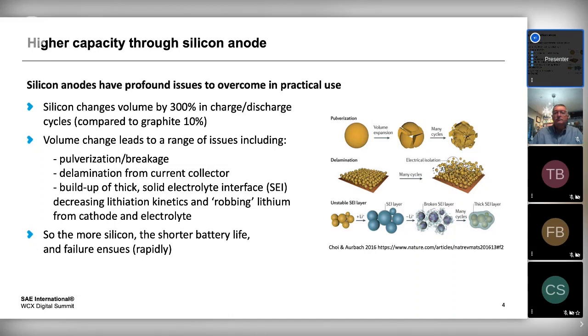What happens is the silicon particles themselves will pulverize and break under that volume change, and they won't go back together. The entire particle system will try and lift off of the copper current collector. And more importantly, when the particles break, they increase their surface area. That extra surface area means more lithium gets sucked out of your electrolyte and your cathode to form the solid electrolyte interface, which is the thing that coats the particles the instant you charge a battery for the first time. Once that lithium's gone out of the system and it's stuck in a solid interface on the anode particles, you can't get it back. So you just lost, say, 10 to 20% of your battery capacity, which means you just lost approximately 10 to 20% of your range in your electric vehicle. So this is the problem with silicon.